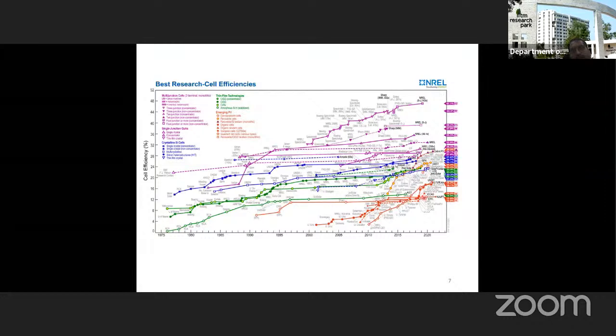The ones at the bottom of the chart are all the organic solar cells, okay? They have about 17 to 18% certified efficiency. But the advantage with these is that they are easy to make, whereas the ones in blue need specialized equipment and a clean room and so on. So the investment is huge with respect to these solar cells. We actually need semiconductor technology to develop this, whereas the ones at the bottom are very easy. In anybody's lab, we can do this in no time. Fabrication wise, they are very easy and they involve cheaper materials. But the downside is their energy harvesting efficiency is not that great.